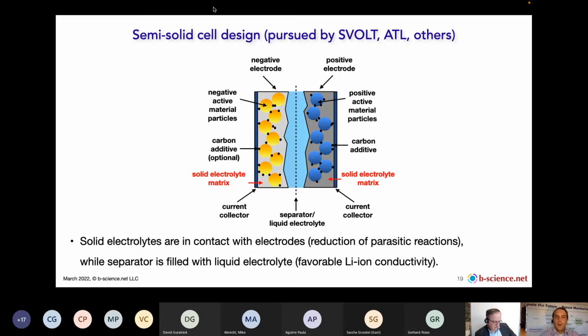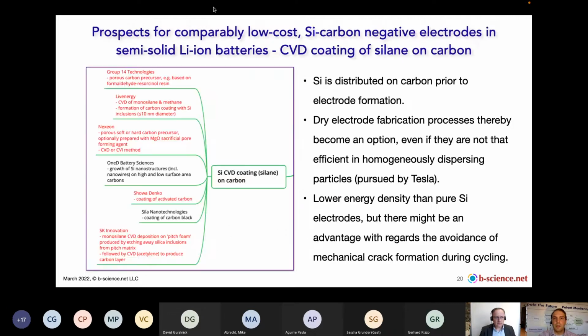processes tend to occur. And so these companies, when they coat the electrodes, or one could also produce them in a dry way, use solid electrolytes to be in contact with the active material, and then they construct the cells in the same way as is done now. And so from a chemical point of view and from an interface point of view, this I think can make a big difference, and is a way of combining the positive aspects of the solid electrolytes, avoidance of parasitic reactions, and of liquid electrolytes, which retain favorable lithium-ion conductivity, especially between the electrodes where there is a relatively large distance.